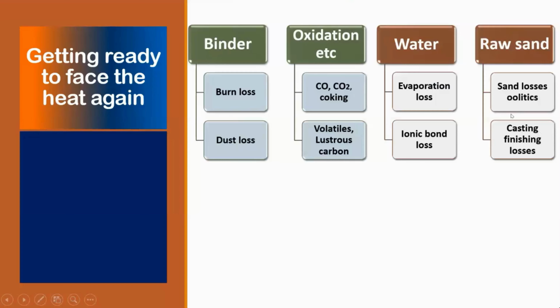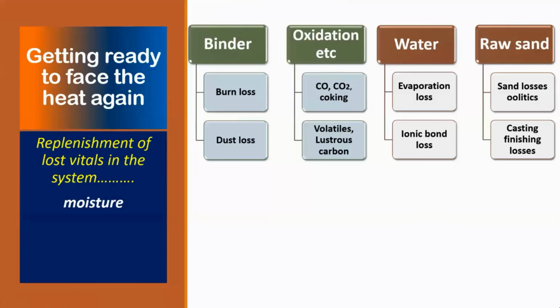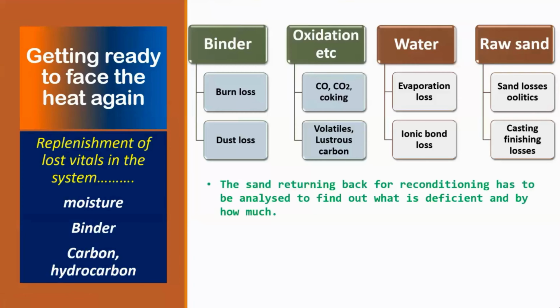So these losses will have to be replenished. This water has to be replenished. These carbons and volatiles have to be replenished. These burnt and extracted losses have to be replenished. So replenishment of lost vitals in the system consists of moisture, the binder, and carbons and hydrocarbons. The return sand for reconditioning has to be analyzed to find out what is deficient and by how much.